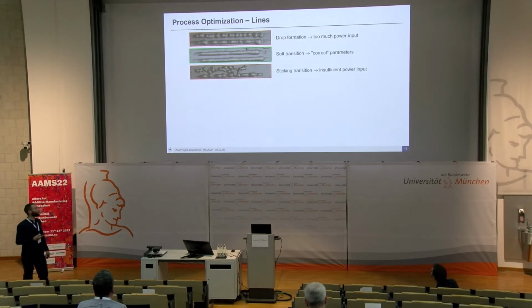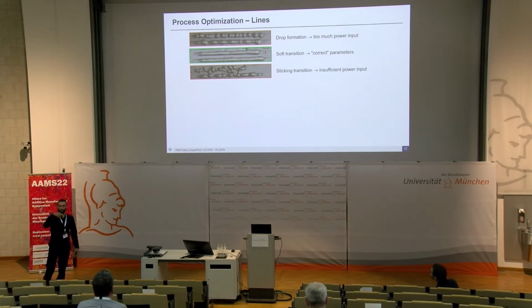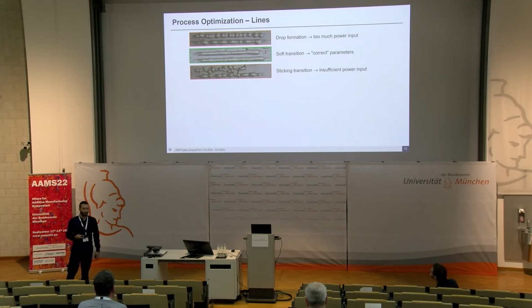So what are the normal formations in DED processes? We first have the drop formation. When there is too much energy in the process, the wire begins to form drops and drip on the surface plate. Then we have the soft transition with maybe an optimal parameter set. And we have the sticking, when the wire is stubbing on the surface plate, when there is less power in the process.